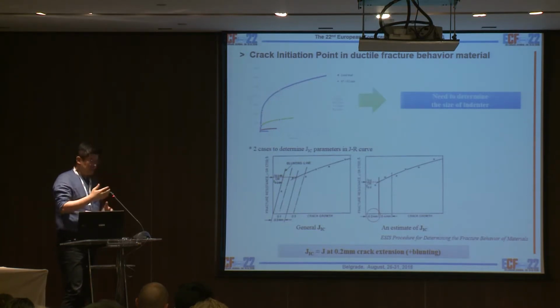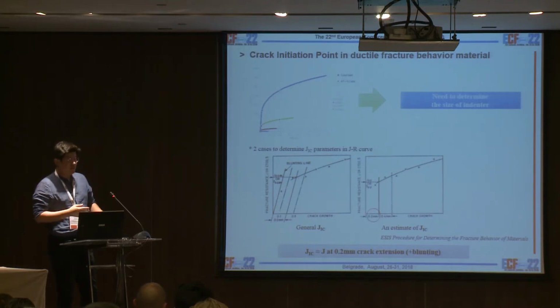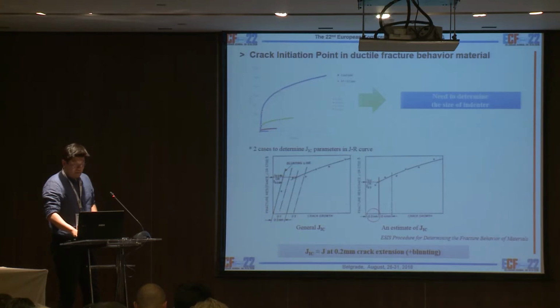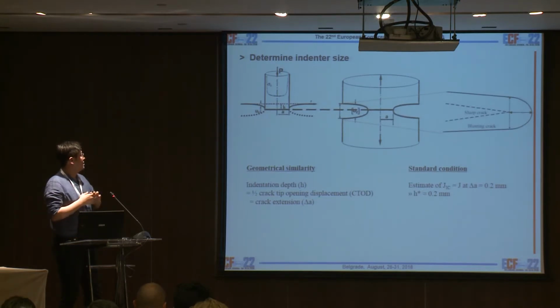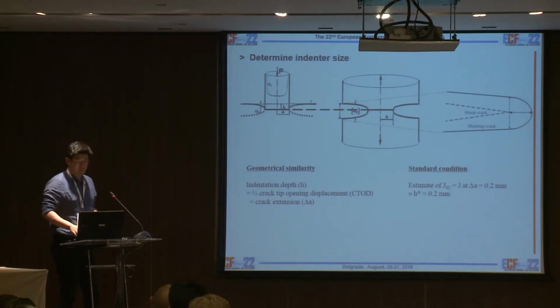When we determine the J1C, the standard suggests a 0.2 millimeter blunting line, which means the 0.2 millimeter cracks are ignored. So from this geometrical similarity, if we penetrate 0.2 millimeter, then it can be thought that the blunting crack is 0.2 millimeter. So we focused on the penetration depth H star as 0.2 millimeter.